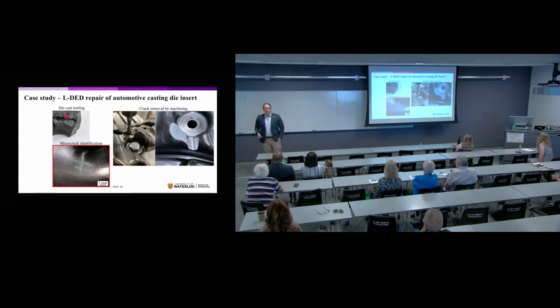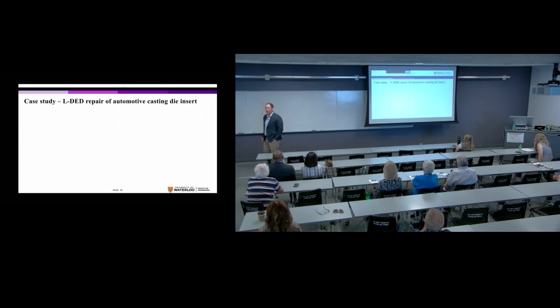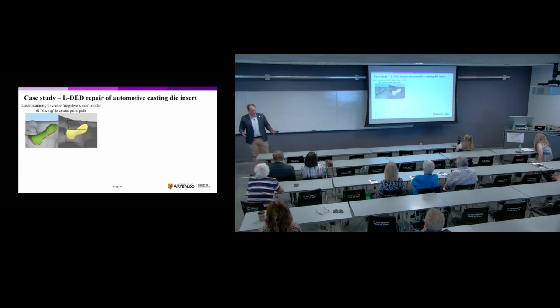So what we did is we took this piece of tooling, we put it into our manual mill, and we just simply milled out a groove to completely remove the crack. And that's what we can see over here. So we just milled it out so that the crack wasn't there and it wouldn't grow any further. We then took this tooling and we laser scanned the whole surface. And once we had that digital model of this tooling, we compared it with the digital model from the original piece of tooling. And by comparing the two, we could create what we call a negative space model. And that's what we can see here in the green. So essentially, the comparison showed us where in our scanned tooling we're missing material.